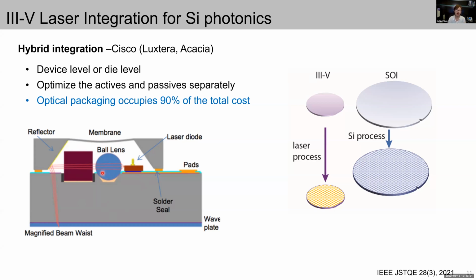Efficient optical coupling of the III-V to the silicon photonics waveguides usually relies on alignment with precision in the lower micrometer or even sub-micron range. So this often requires slow and expensive active alignment techniques, where the coupling efficiency is pretty low. And moreover, additional devices such as microlenses, prisms, or micromechanical carriers are needed to adapt the mode field size and the emission direction of the III-V light source to that of the silicon photonics circuit, and that leads to a large footprint and limited scalability.